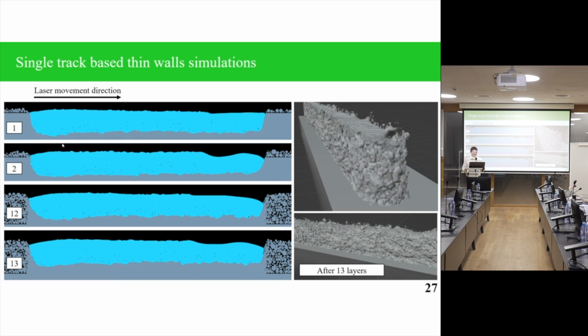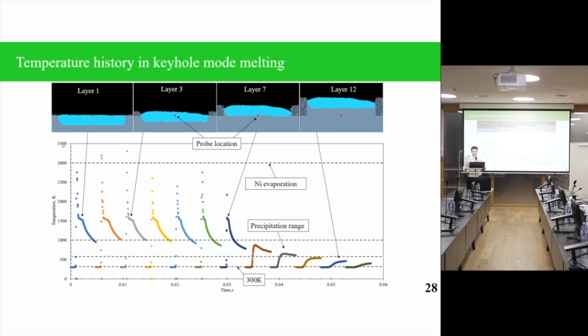So the second numerical experiment involved the simulation of thin-walled samples, and the procedure looks like in the experimental study. So we make the powder bed on top of the substrate, we remelt it with laser, then on top of this geometry we add an additional layer of powder and remelt it with the previous geometry. So this numerical experiment was run until we do not have any significant temperature rise at the substrate level. The probe location is shown with a red point, and in this point the temperature was measured for every layer, and we can see after 12 layers this temperature rise was insignificant.